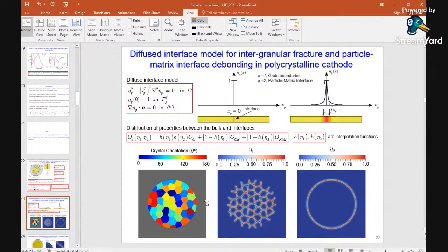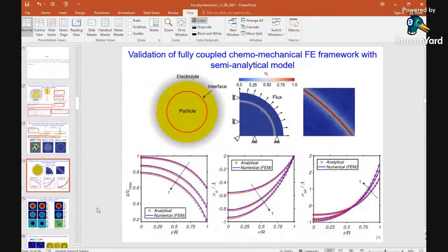First, we see that in the structure, we have a very nice polycrystalline structure generated by our own in-house developed code, and we assign a crystal orientation. So we can incorporate the statistical information from experimentally observed crystal information, and then we developed a diffuse interface for the grain boundary, and between the matrix, the gray region is the matrix. That can be a polymer binder or any solid electrolyte. You can consider anything of that. We have two types of interfaces here. One is the grain boundaries, and the other is the interface between the particle and the matrix. Both are characterized, and both have different mechanical properties.